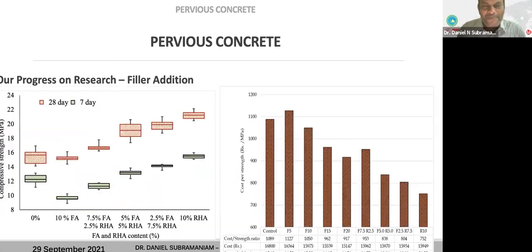In this one, instead of having just one ash, we thought of adding fly ash and rice husk ash together, so that the total substitution is 10%. We don't want to go more than 10% substitution, so we keep that as a benchmark. We try to put the two different ashes to see whether we can get a higher strength. And we found that we could attain about 20 to 21 megapascal with 10% RHA.